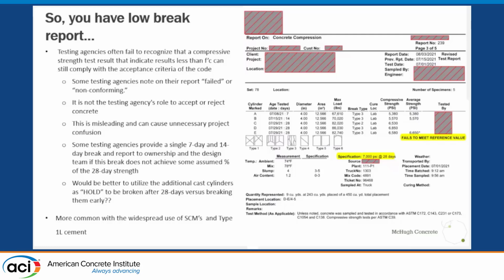But we don't have any reserve cylinders afterwards, so we're now left in a pickle. It would have arguably been more useful to cast additional cylinders, or potentially not break the 7 and 14 for this example. So we would have had that additional data. Having those hold cast cylinders is really, really important when you're in this discussion about do we have an issue, do we have a problem?